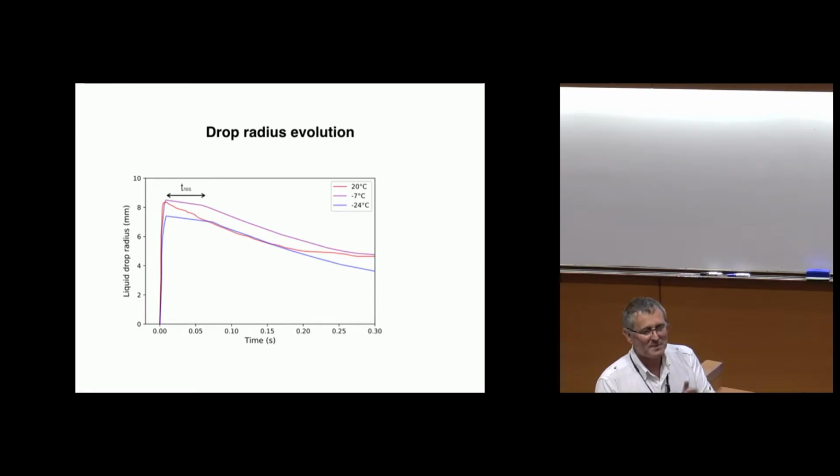What people observe, for instance, there was a quasi-static experiment at MSC in Paris, where by making some argument on the heat flux at the contact line, they were arguing that the contact angle should be 90 degrees. And I think when they measured it, it was 87. So we are probably closer to this 80-something degrees than 0. And I have no clear understanding or clear explanation of that.